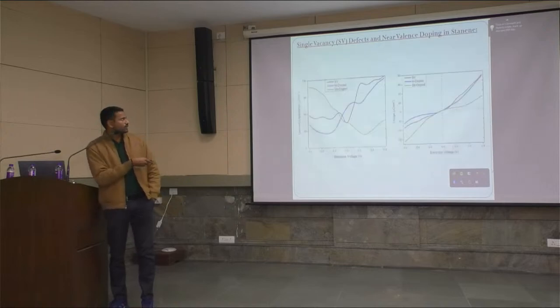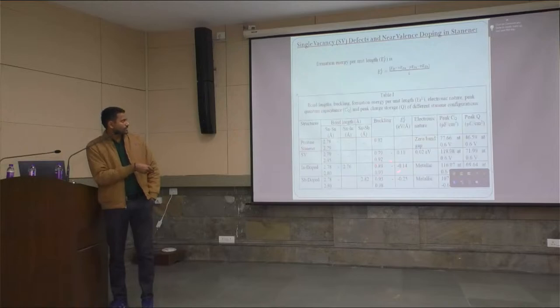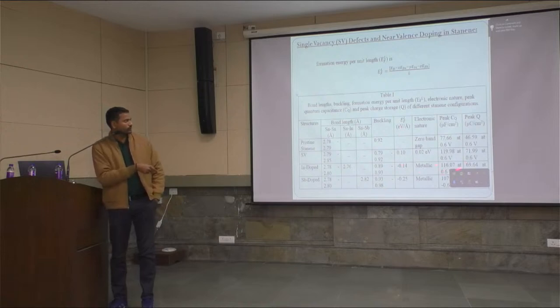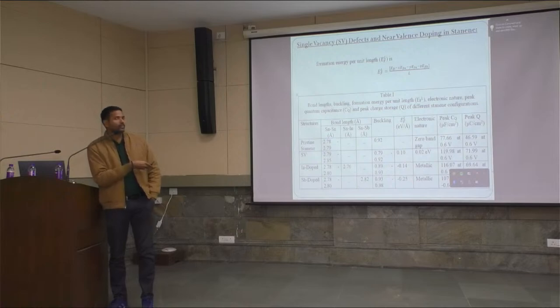And positioning the indium and antimony has improved the stability. We can see the negative value of the formation energy here. And the quantum capacitance also increased very much. It is 116 microfarad per centimeter square in comparison to pristine stanene's 77. Similarly, for antimony, it is 107.